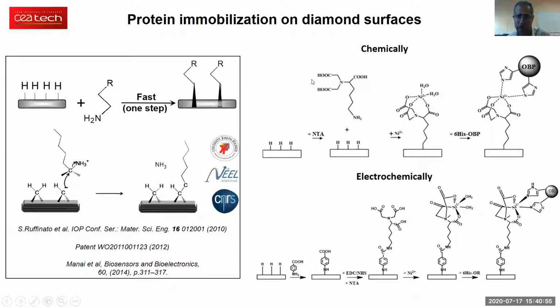So an example of applications is this nitrilotriacetic group here, NTA, that I'm sure many of you know because it's used quite commonly to purify proteins. And so this group here is terminated with an amine. We can attach it in this way to the diamond surface. And then we can expose it to some metal ions like nickel. It will form this complex, which will then interact with histidine tags that are attached to the proteins. And the beauty about these tags is that they can actually be located on the protein. That means we can actually control the orientation of the protein on the surface.